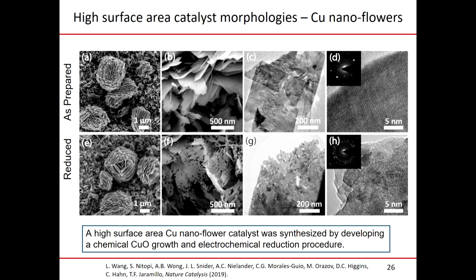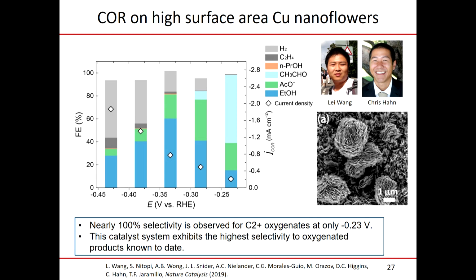And so based on the supercapacitor literature, and Veronica gave a really nice talk earlier today on that, we just found some really nice preps for some really high surface area copper. And so this is what Lei did, and we tested it out for CO reduction in base, kind of throwing everything at it. CO reduction in base with a high surface area material. We can get the chemistry to go at very low overpotentials, only minus 0.23 volts versus RHE. And interestingly, it is almost 100% selective for CC-coupled oxygenates. Because you're operating so close to equilibrium, you're not reducing it all the way to the hydrocarbons.